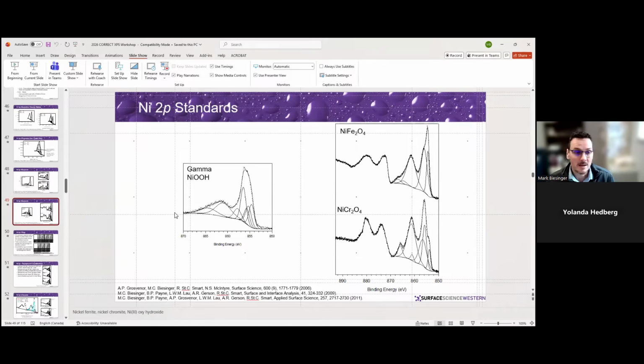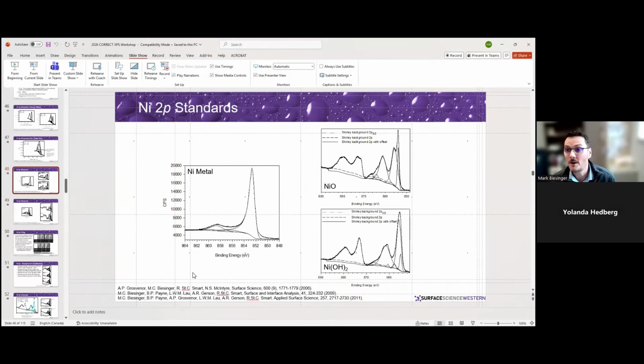What we're seeing a lot in the literature, far too often, and this kind of talks about your question, is we will see a spectrum that looks like nickel oxide, maybe a little bit of nickel hydroxide, and they will have labeled that this peak is nickel 2 and this peak is nickel 3. And based on that, their whole paper might be based on the fact that they're seeing nickel 3. I've seen this a lot in battery technology papers where they've got nickel 3 present.